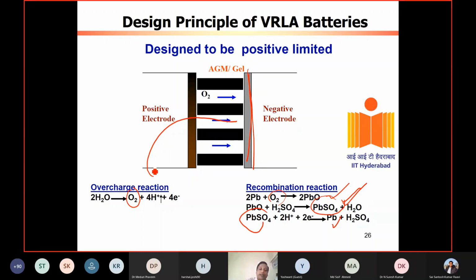So what it will do is, once it combines on the negative electrode, oxygen doesn't escape. So it increases the hydrogen evolution potential. It reduces the hydrogen evolution. Generally this happens more around 2.25 to 2.3 volt in a lead cell. And generally oxygen evolution starts around 2.4. If you don't have oxygen recombination, it increases to 2.45.